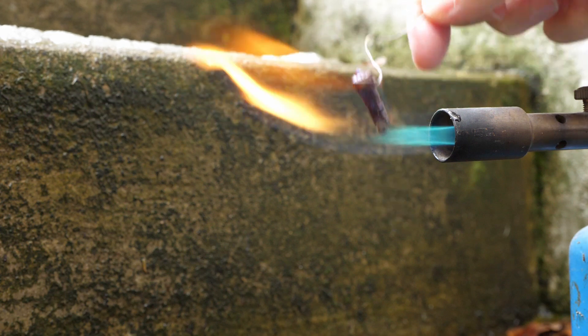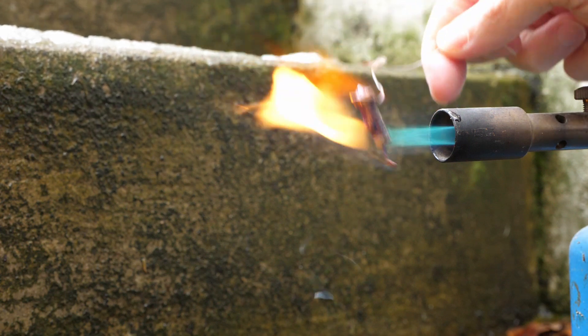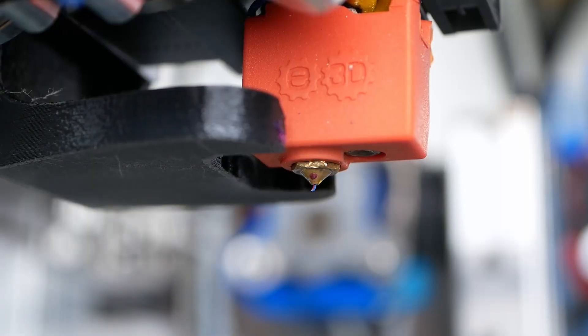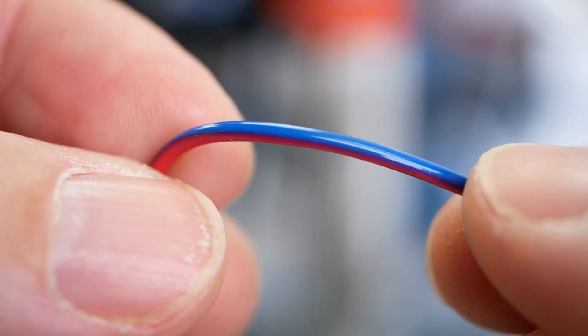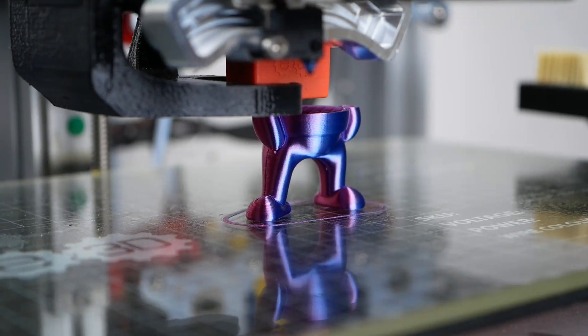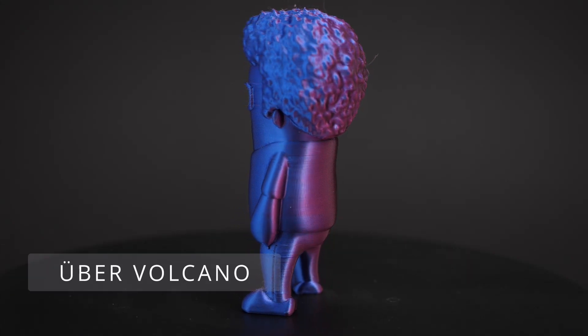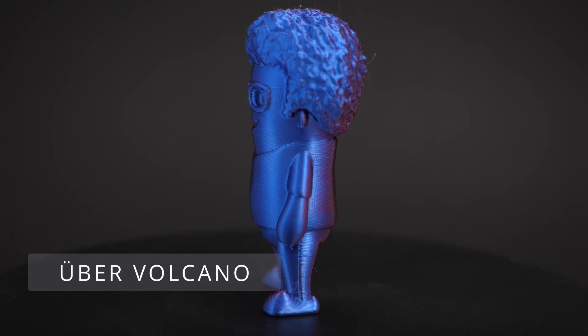Since I couldn't resolder the joints with the plastic inside, I burned out the nozzle with a torch, effectively getting rid of the solder and the wires, and resoldered everything. Nothing leaked this time after heating the nozzle to only 210 degrees Celsius. And even despite the 6 wires in the flow path, it didn't seem like a lot of mixing was going on. Also, my mini Stefan printed really well and there wasn't even a lot more stringing visible than with a standard nozzle.